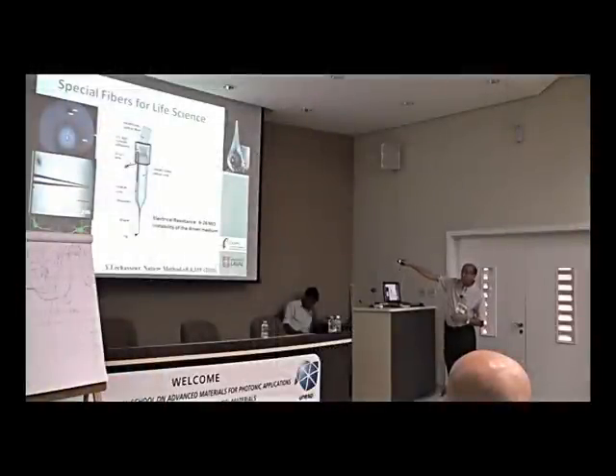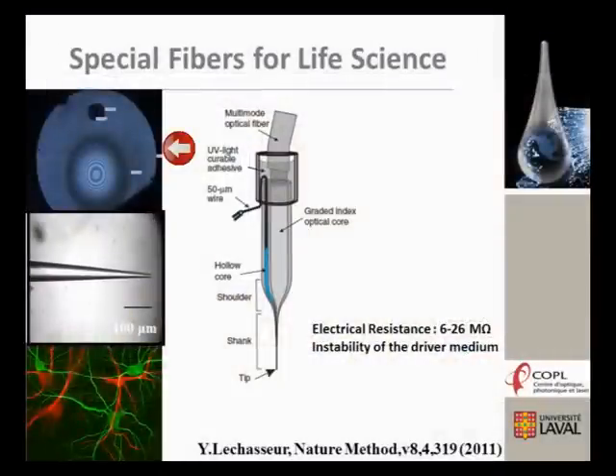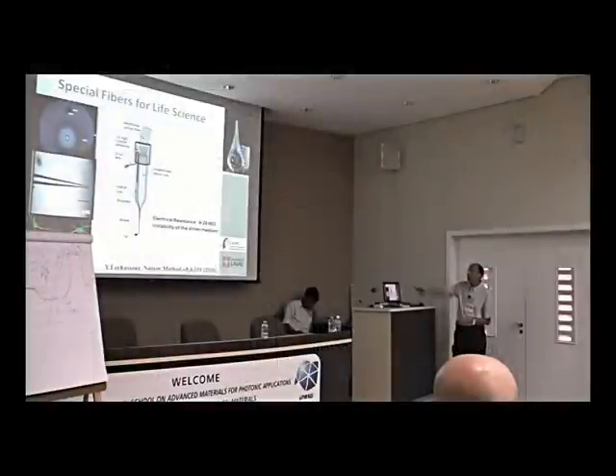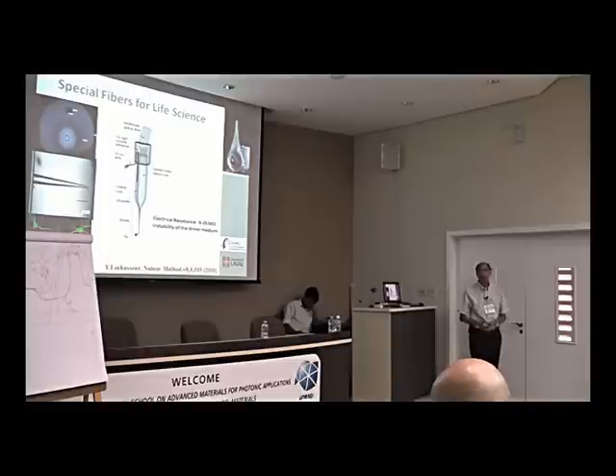This is a gradient index fiber with a hole here. This hole, this core, is filled with this solution for electrical measurement. The electrical resistance is around 6 to 26 megaohm. One drawback of that is the instability of the electrolyte medium. We have been working together since they published this work last year, on how to enhance the quality of the fiber in the way to transfer this technology to a company.